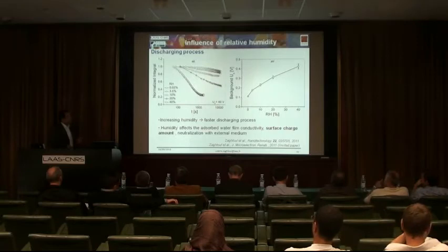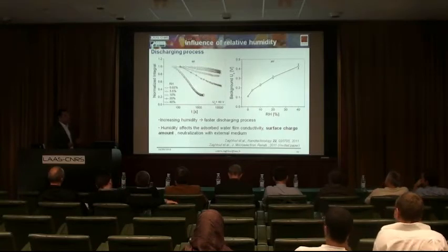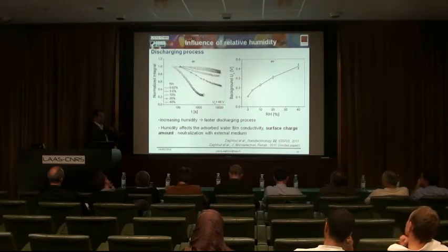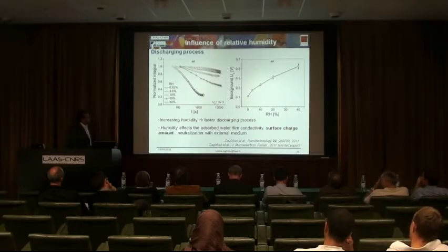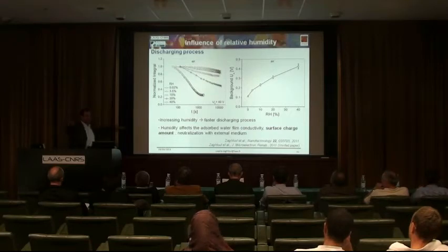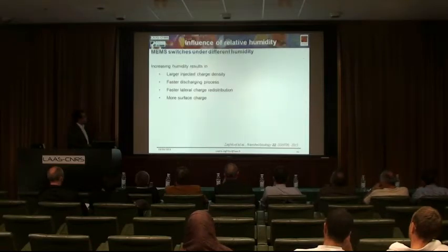The other important point for the humidity actually is the surface charge. This is the background voltage, which we measure actually at different humidity, where no charging is there. We just measure the surface potential over non-charging area. You can see easily that we are measuring different background potential with humidity. Increasing with the humidity means we have more surface charge with humidity. This actually could explain why we have faster lateral spreading over the surface.